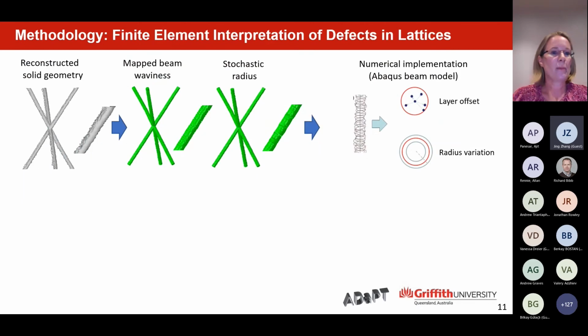From a finite element point of view, how do we treat this? So if we're looking at trusses, we work with beam models just for simplicity purpose and for easy defect mapping and stochastic variations. So we can map the beam waviness by introducing layer offsets. We have beam elements that are in the order of the layer thickness, so that works, and it's still fairly small computational effort.